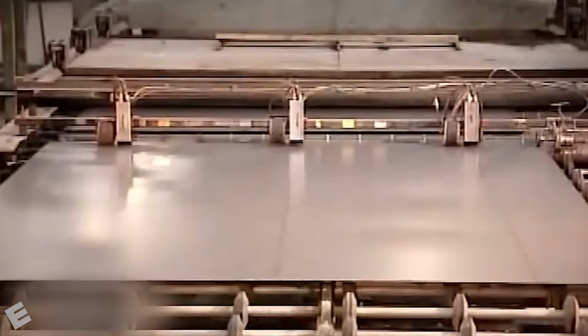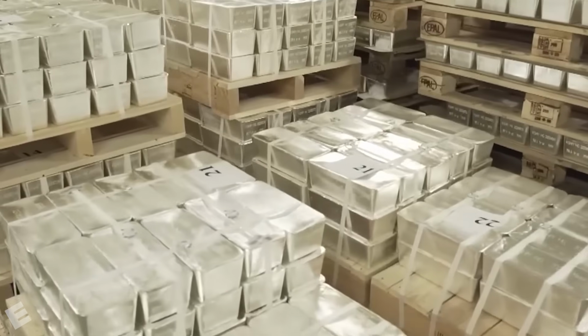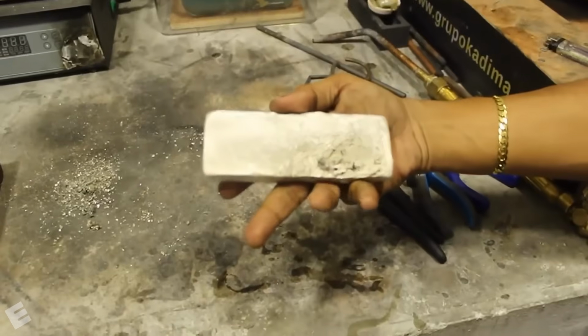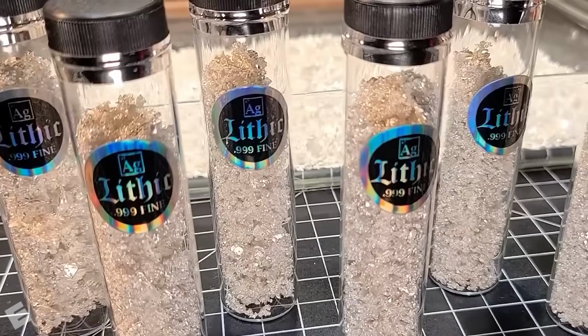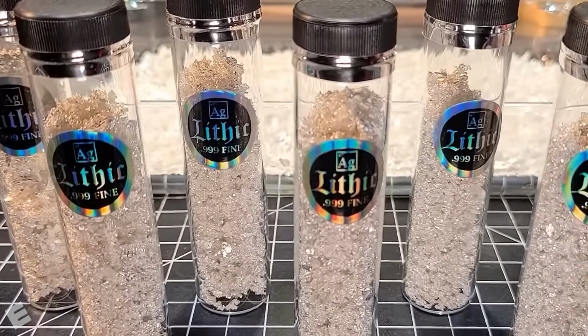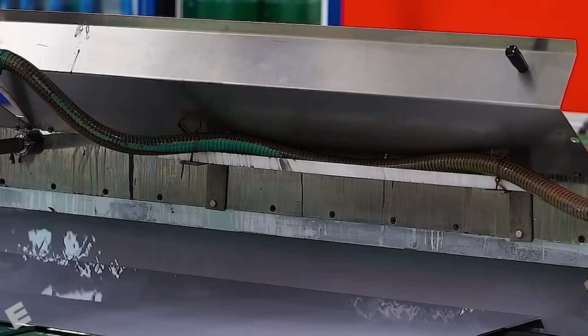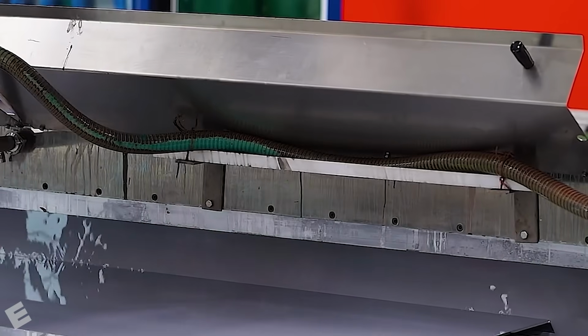The controlled reaction causes an extremely thin layer of metallic silver to form directly on the previously polished and cleaned glass. The transformation almost appears magical. A transparent sheet of ordinary glass gradually becomes a reflective surface capable of reproducing images with remarkable accuracy and clarity.